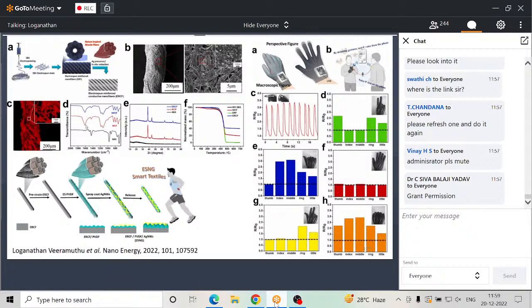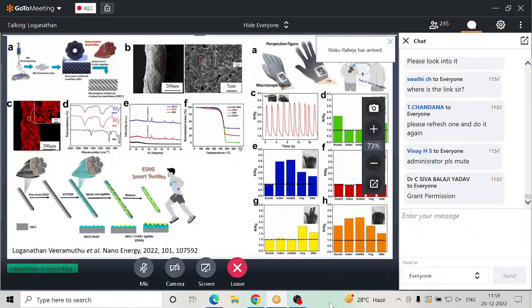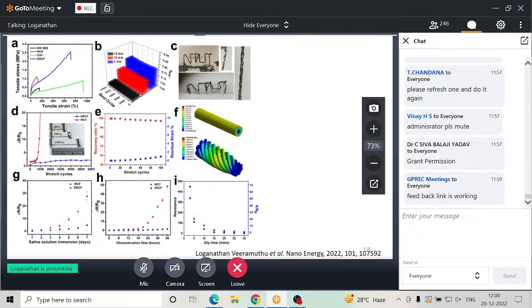And yeah, here we can see how the silver nanoparticles are getting interconnected by using EDS, and we studied their FTIR peaks and XRD as well and TGA to see the thermal stability. And we take this kind of ERCF structure, and then we prepare this kind of smart textiles by using electrospun PVDF structures over that. And here we can see the differences in mechanical robustness among WCF and ERCF values, and it is quite vivid that we are able to achieve very good stretchability up to 900%, and it is sewable. Even we can sew them in the textiles, and it's quite good.